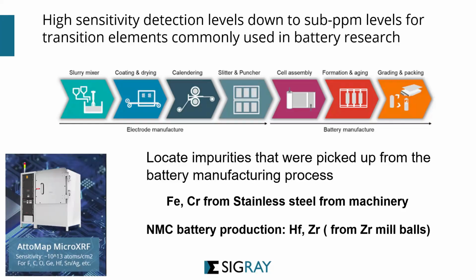So this high sensitivity down to sub-ppm level can be effectively leveraged in the battery industry. We can locate impurities that are picked up from different manufacturing lines. For example, if you find iron and chromium, therefore you have the ratio of a stainless steel from a certain machinery. Or in NMC battery production, if you see traces of hafnium or zirconium, then you know that it must come from the zirconium mill balls in the process.